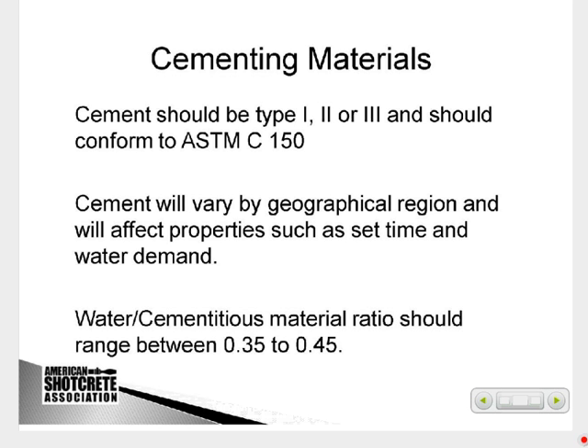Cement, basically, we use the same as concrete. We're using the types 1 and 2, typically, rarely a 3. 3 is high early, and we don't generally need that because we have a lot of cement, and we typically use a silica fume or microsilica that adds strength. Water-cement ratios are low, 0.35 to 0.45.